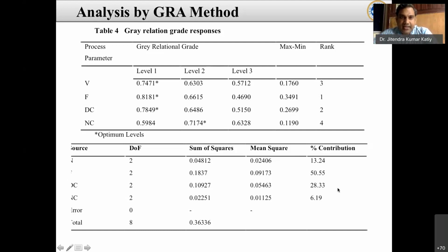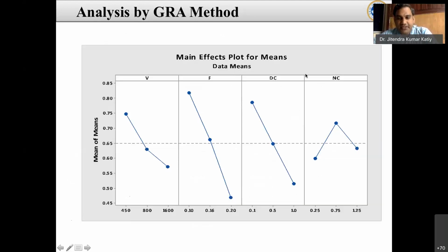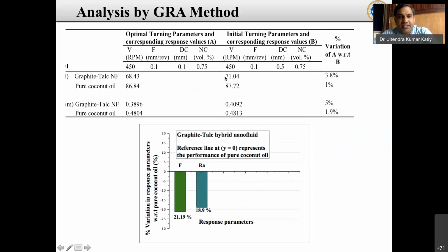These are the mean effect plots which we obtained by the GRA method. Here I obtained 450, 0.1, 0.1 and 0.75, from maximum to minimum. That is the main thing. These are the optimum parameters obtained by the GRA method, and we performed our test with these optimum parameters, and then we can check the corresponding response values.